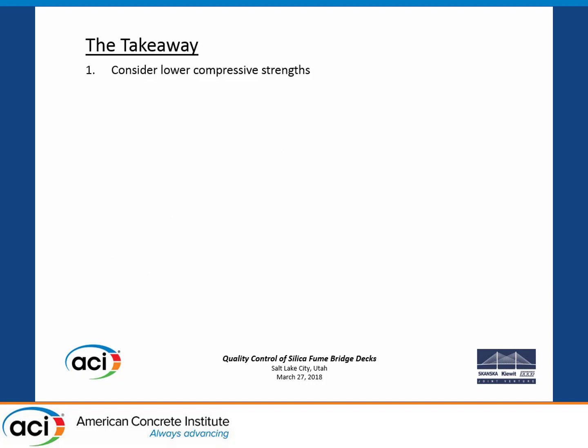So, the takeaway, you know, too much of a good thing. There should be a balance between compressive strength and what you need. I mean, we needed 6,200 as f'c critical. We got 10,000 in 56 days. The same with the silica fume. Maybe you want to use less silica fume. I mean, we got 280 coulombs. You know, 900 would be good.